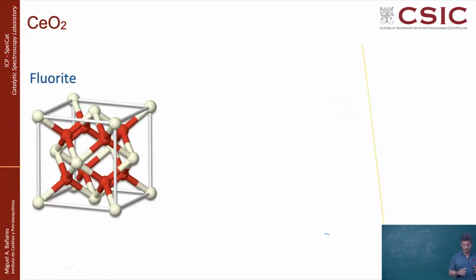Now, ceria is a very interesting and versatile system. And what we have also been doing with ceria is to study its application for other reactions, mainly from the experience, because ceria is a highly reactive oxide. The reactivity depends on many things, like the exposed phase it has, or many other variables. But it is also tuned by who you support at the surface of ceria. For instance, in the case of vanadium, basically what vanadium is doing is to make ceria a moderate combustion catalyst, moderate oxidation catalyst. Ceria is running combustion, but vanadium ceria moderates it and then allows you that if you are flowing ethane on ceria, you get CO2, not a big deal. But if you flow ethane on vanadium ceria, then you are getting ethylene. So you are making it selective.